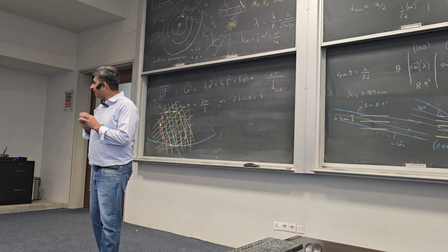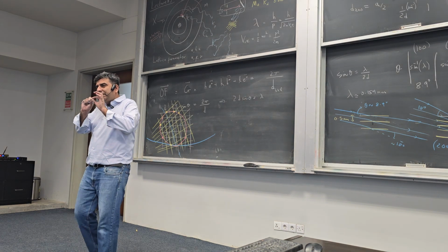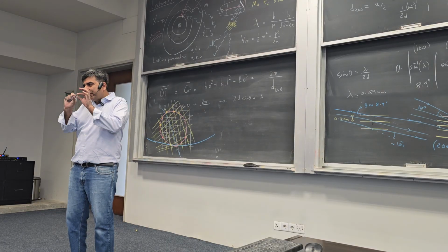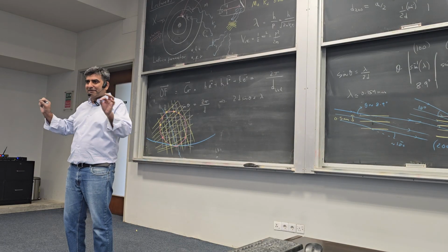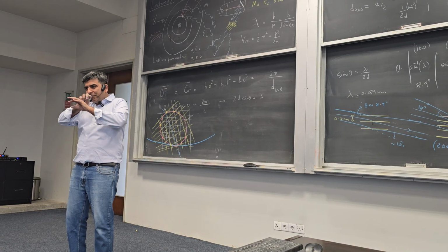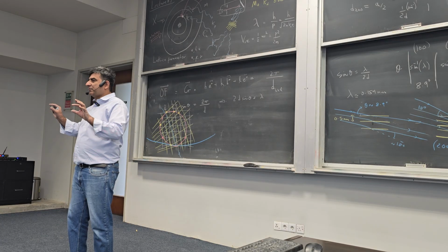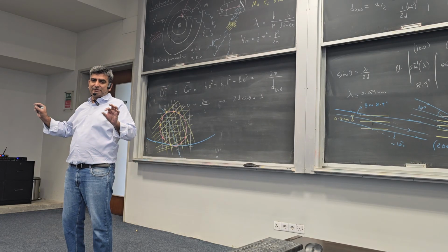So that's why if you want to do diffraction studies with electrons in an electron microscope, transmission electron microscope, you need very thin specimens of the order of few atoms layer thick, like 1D, 2D, or a few layers, bilayer, trilayer. Very thin specimens are required of the order of nanometers.